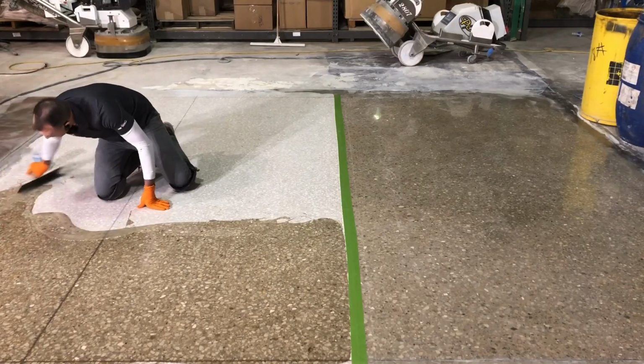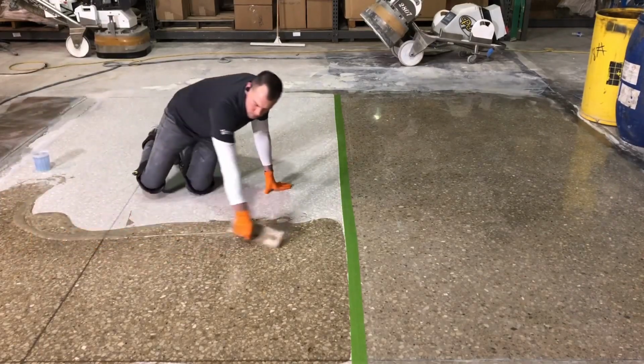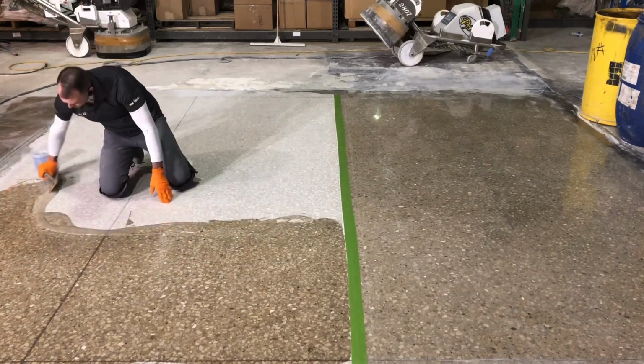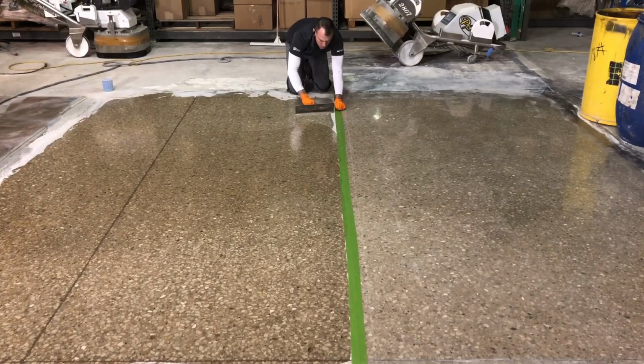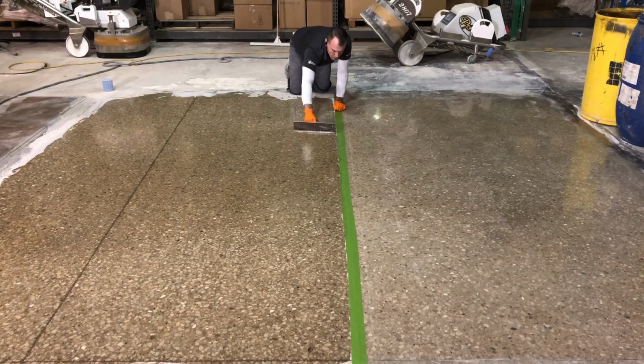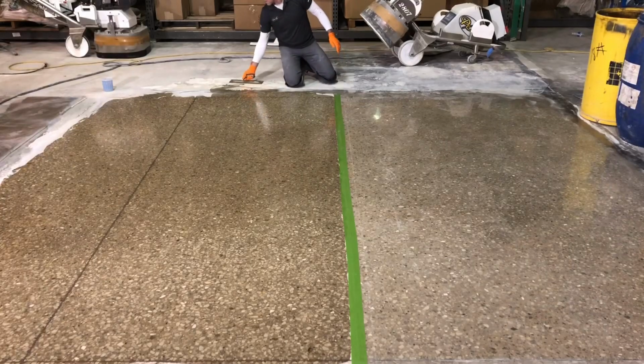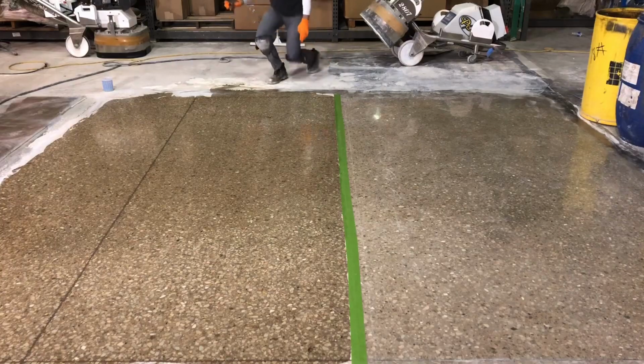The goal of the epoxy skim is to fill in any gouges or marks from prep, any of the pits or the holes that we know are present in the slab, and then to also seal off that surface. By filling in any of the minor imperfections in the floor, we're eliminating the possibility of those defects telegraphing through the top coat. The entire epoxy system is only going to be about 25 mils. So that much coating may sound like a lot, but it's very likely that anything that wasn't filled in or patched in with that skim coat would more than likely show through the top coat of the floor.